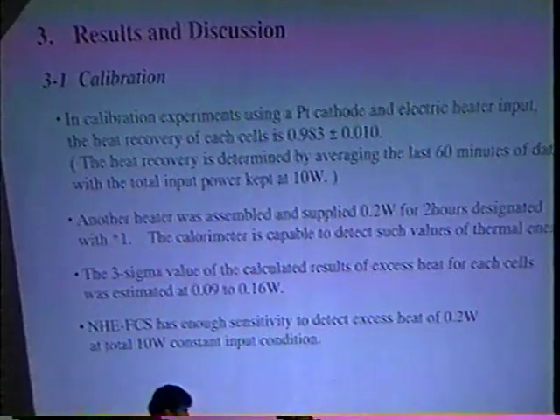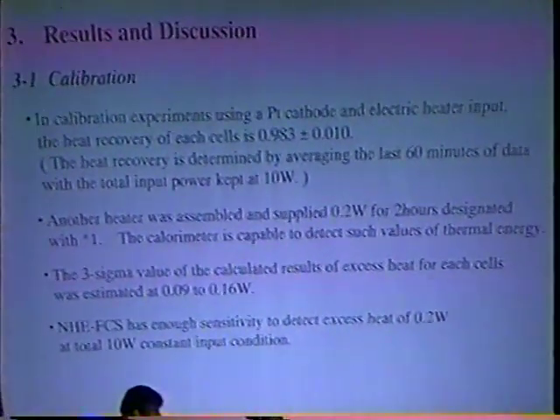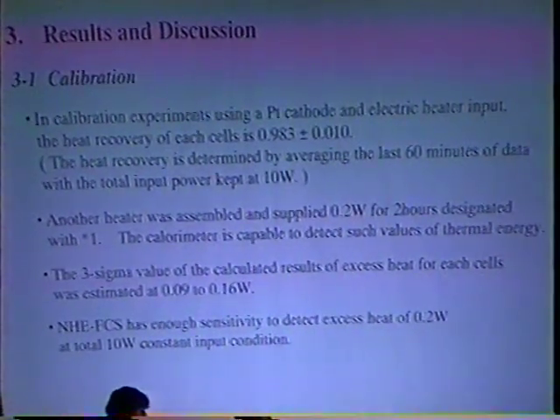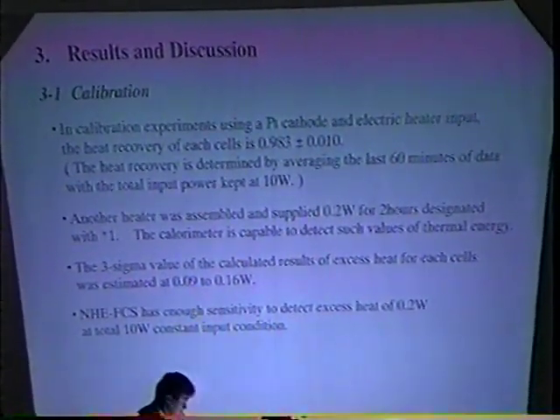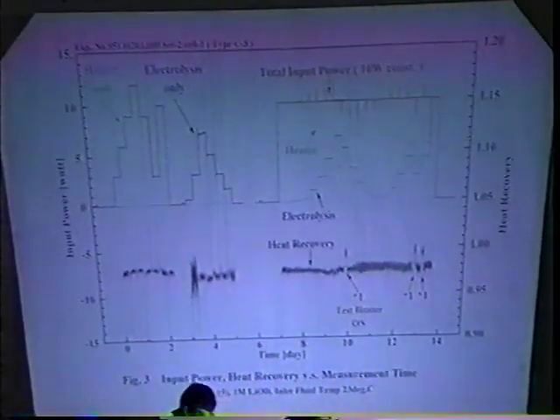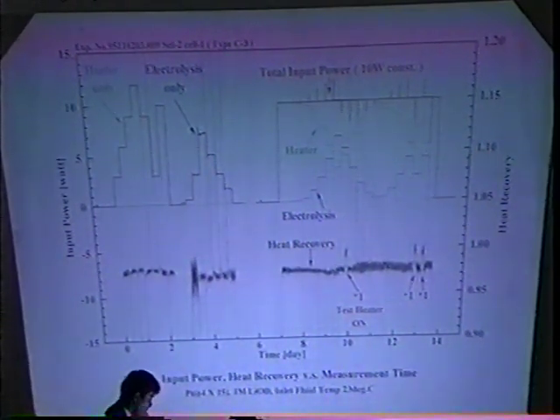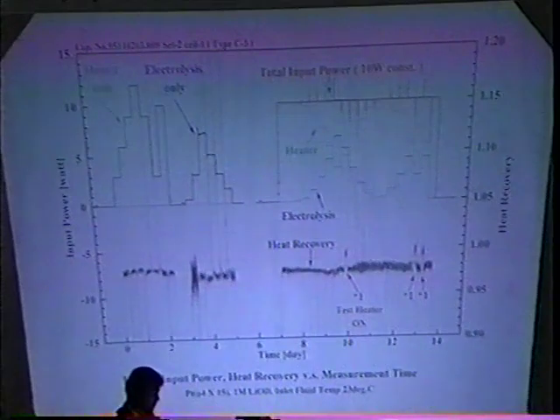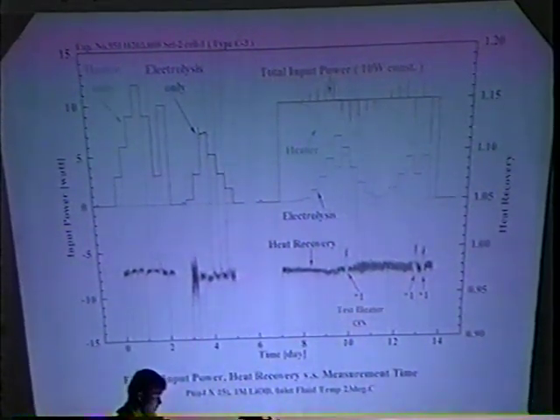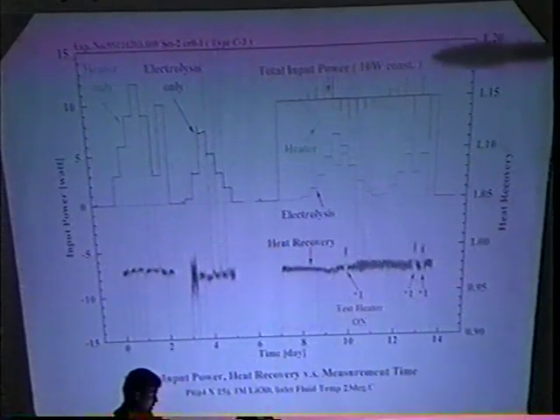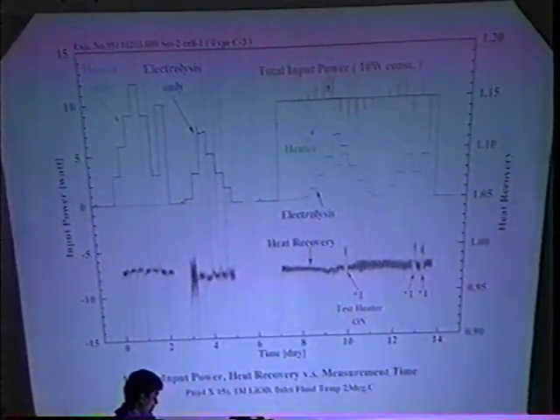In calibration experiments, a platinum cathode and electric heater are used, and the heat recovery of each cell is 0.983 plus or minus 0.010. This figure shows the result of a calibration experiment using one type C cell. Red line is the total input power. Green is that of the electric heater. Blue is that of electrolysis. And black is the heat recovery.